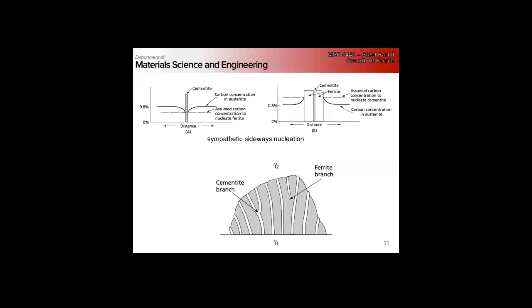Now the part that I managed to confuse myself about, because I don't know how to read a reciprocal graph. If we think about what's going to happen at higher temperatures, we have less driving force for growth. The closer we are to the eutectoid temperature, the less driving force for growth, but we're also going to have higher diffusivity, higher mobility.